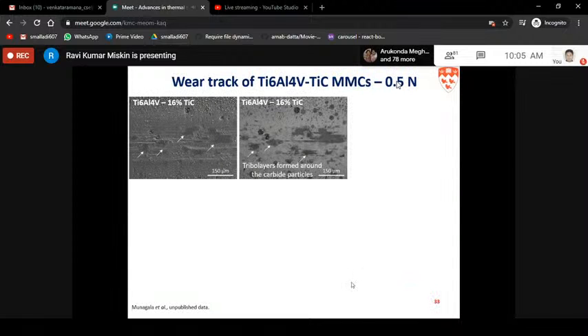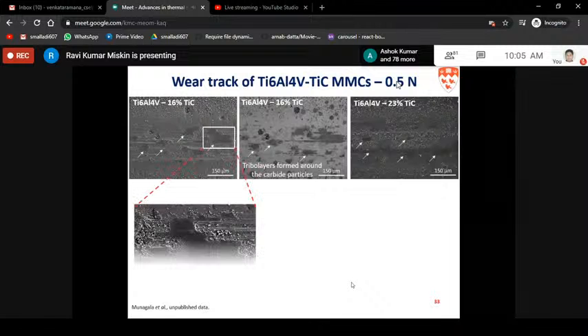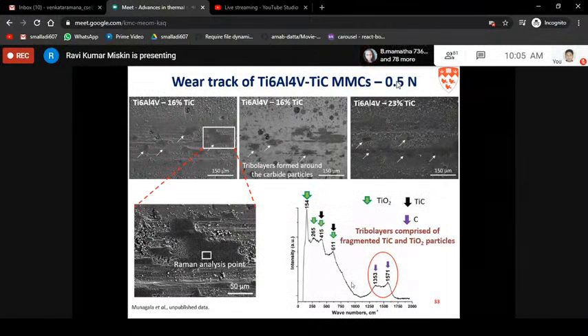Yeah. Now if you see, in case of titanium 64 TiC MMCs, on the wear track, when you have carbide particles, you don't see such groove marks, but you see there is a protective layer being formed. If you look at the left side, top image, you have those islands of what we call tribo layers, because they're agglomerated oxide particles. Once you have those titanium carbide particles, it stabilizes your wear process, and then you have this protective layer formation. Once you have this protective layer, you're not exposing the subsurface.